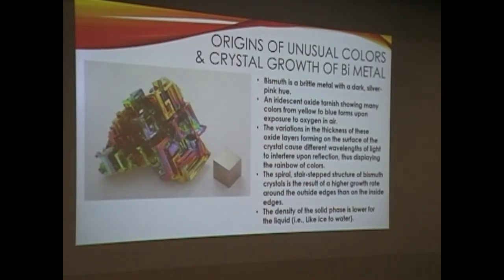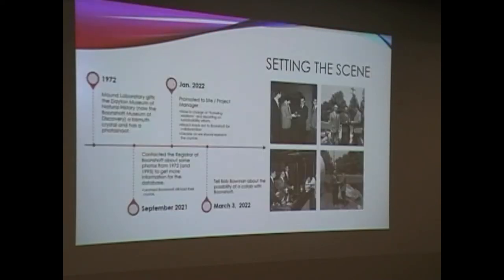Now, where did the color come from? And this is a photo, and you're actually going to see a lot more examples. It's this chunk of metal, but on the surface, it oxidizes and forms a thin, transparent oxide layer, and light strikes it and gets reflected back. It gets reflected in combination with color, and because you grow the crystal, it tends to expand outward by the growth pattern, and the variation of thickness will cause the different colors to be observed. Part of it is due to the fact that the crystals are lighter than the liquid, so they have a tendency to grow and expand out in this pattern. So this has been my orientation of the properties, and now I'm going to turn it back over to Jackie